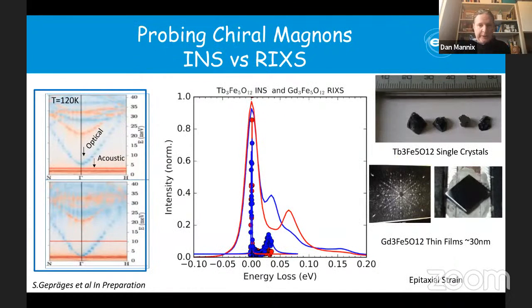So I can show here some of the results we measured with the neutrons. The width of the elastic line here is essentially a measure of the energy resolution. You can see that the energy resolution is so much greater for the neutrons than for RIXS. However, you can see similar effects here, this kind of switching over of the differences between left and right. It seems to reflect also the polarizations that were determined with neutrons.